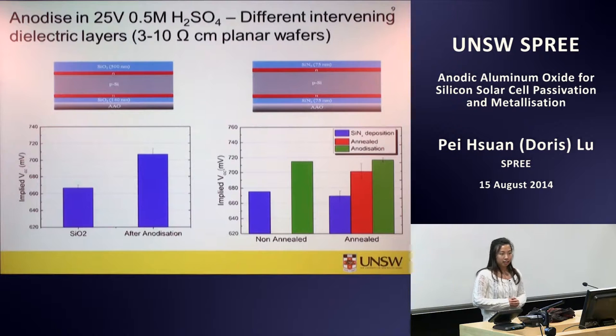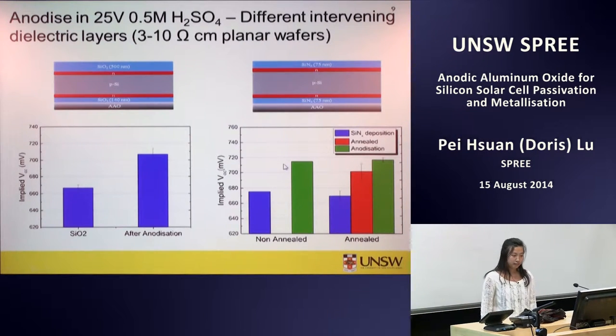At the beginning, I tried my experiments on the planar wafer with a lightly doped phosphorus diffusion. We found that after anodizing a layer of aluminium on top of silicon dioxide, there is a 40 millivolt improvement on average. Compared with anodizing on a layer of silicon nitride, without a middle anneal step, there is a 47 millivolt improvement on the sample with an intervening layer of silicon nitride, which suggests anodization might work as an anneal process, so that an anneal process may not really be required.